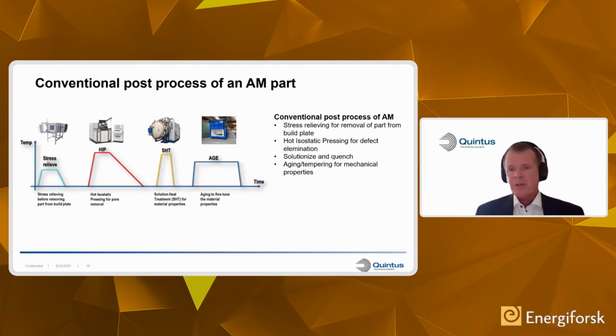I mentioned before high pressure heat treatment. Typically a thermal process for not only AM parts but for many parts could look like this, where you would have a number of independent thermal processes. You would have stress relieving before removing the parts from the build plate, and then you would have a HIP cycle performed, and then you would remove it from your HIP press, and then you would have a solution heat treatment. And finally, as a fourth step, you would have the aging process.